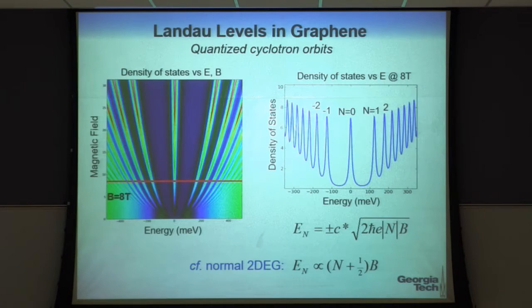Okay? So I better not spend too much time, but just if I look at the density of states as a function of energy and magnetic field, these quantized orbits, the cyclotron orbits in the material, they're quantized essentially because I have to have the wave function wrap back onto itself. Gives me discrete energies then, because I need an integer number of wavelengths around the circle. It gives me discrete energies, and they all depend on the magnetic field. So that's what this dispersion is, that as I increase the magnetic field, the spacing between these states gets larger and larger, and the intensity of this is the density of states.